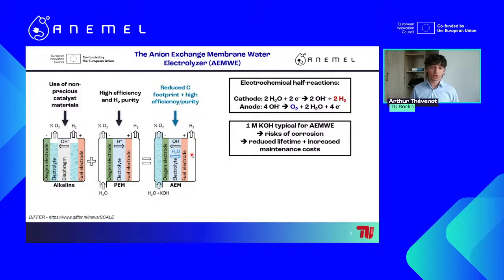The current electrolyte that we use for this kind of electrolyzer is 1 molar KOH. So it's still way less concentrated than for alkaline water electrolyzers, the traditional one. But it's still concentrated enough to have a risk of corrosion of your cell components, which will naturally induce reduced lifetime and increase maintenance costs.